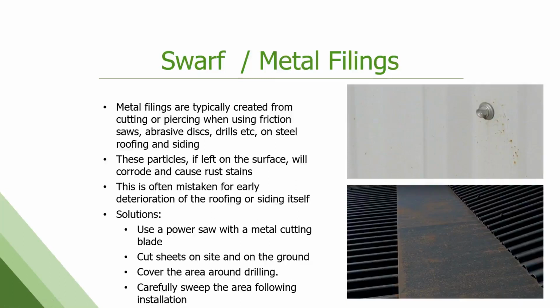Swarf, metal filings. This is an installation issue. So these are little shards of metal left over when they're drilling and cutting on a site, putting fasteners in. If they're not cleaned off the surface, those start to rust. But the complaint that comes in is, oh, my metal panels are rusting. Well, the metal panels aren't rusting. It's what got left on the surface that's rusting. And it's very, very hard to clean off after the fact. So during installation, they need to be very diligent about sweeping and cleaning these up as they go before they start to rust and leave these ugly rust stains on the painted surface.